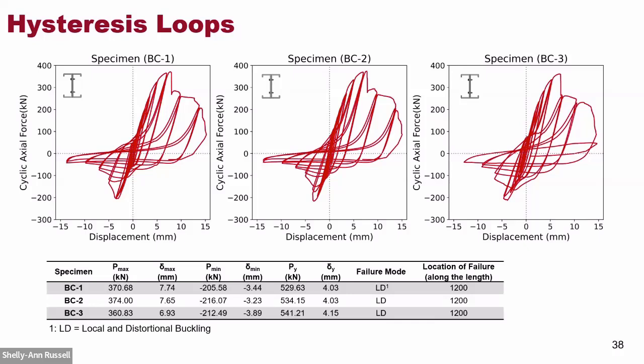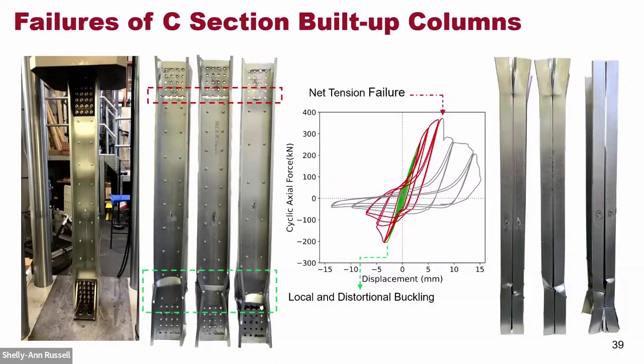The maximum force in tension was 370 with these displacements, and the compressive strength peak points were 200, 216, and 212. Our theoretical calculation was 194, so it's near to these values. And you can see the displacement difference between the compression and tension. So we have quite a difference between these 2 points. And the theoretical yielding displacement of this specimen is 4.3. The local buckling type that happened is local and distortional buckling. And all this damage and failure happened at the length of 1,200 mm. You can see the final specimens after the experiments.